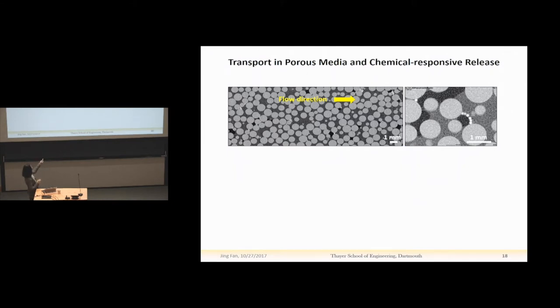So these are the micro-CT images, and these big light gray circles are the glass beads, and these dark black blobs are the oil blobs. And this gray region is the water phase, although we did include some X-ray contrast agent in the water phase to visualize it. And these small white dots are actually the smart capsules we made. Although in this experiment, we encapsulate a high concentration of X-ray contrast agent instead of the surfactant, just to visualize their location, their distribution in the column.